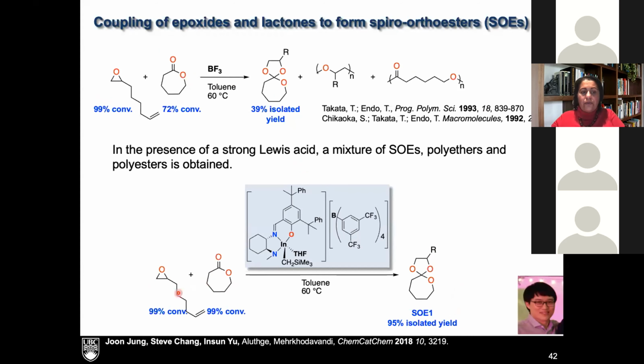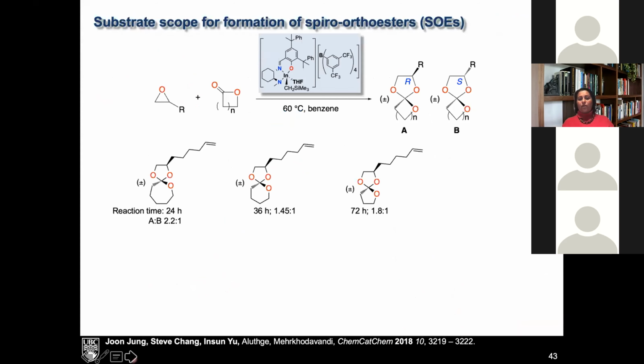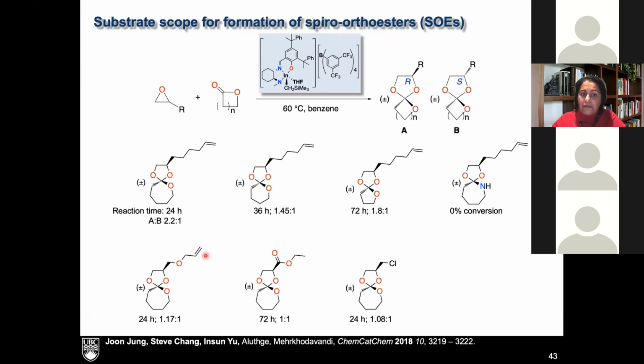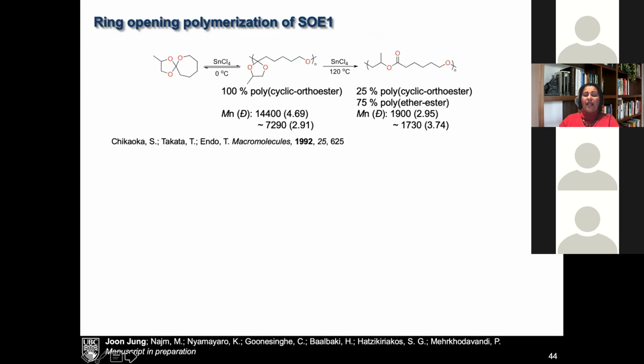And so this was really exciting for us, because now we can expand, we can start looking at material where we are taking this epoxide and looking at different rings. So we're looking at 7-membered, 6-membered, and 5-membered lactones. We can make these. It doesn't work with nitrogen-containing ones, unfortunately, but we can start playing around with the different functional groups. So if we start with a 7-membered lactone, we can change the epoxide. We can just buy a different epoxide and plug that in there, which was really exciting for us. And if we have a bulky epoxide, we can get a single diastereomer. It has to do with the mechanism. And so this was then expanding the kinds of material that we can make, which hadn't been done before in the literature.